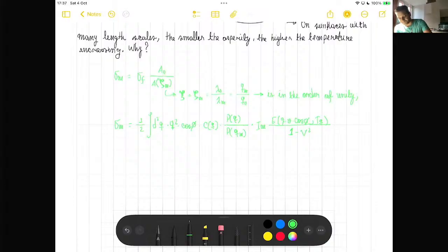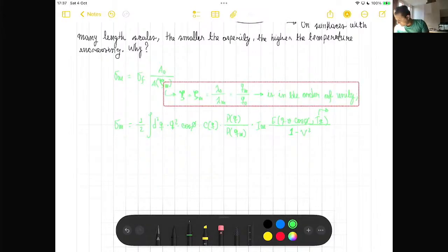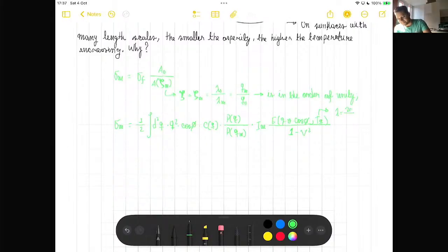T q is an effective temperature in the volume of the rubber involved in the calculation of the contribution to rubber friction from surface roughness on a length scale lambda equal to 2 pi over q.